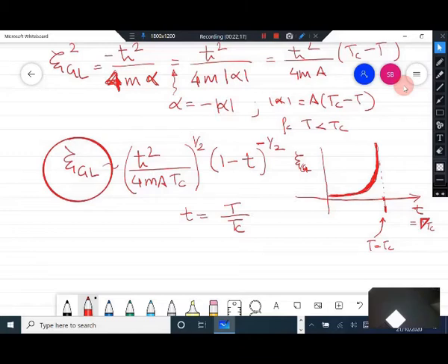Then if you do that, you will see the connection between the xi BCS and the Ginzburg-Landau. They have similar interpretation. Whereas in the BCS theory, the xi corresponded to the size of the Cooper pair. In the case of Ginzburg-Landau, where you are defining an order parameter, it is the distance over which the order parameter is going to decay as you approach a normal superconductor interface.